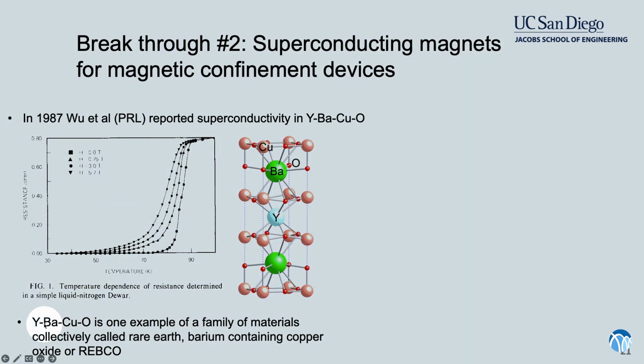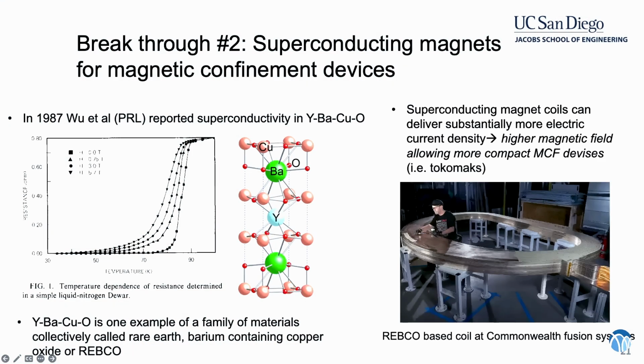So yttrium barium copper oxide is one example of a family of materials that collectively are now called rare earth barium-containing copper oxide, or REBCO. Interestingly and importantly, these superconducting magnetic coils can deliver substantially more electric current than typical coils. And of course, by putting current through a conductor, you get a magnetic field. So this allows a significantly higher magnetic field that can confine the plasma in a much smaller scale, because you can put more current through these magnets and have a much higher magnetic field inside this coil.